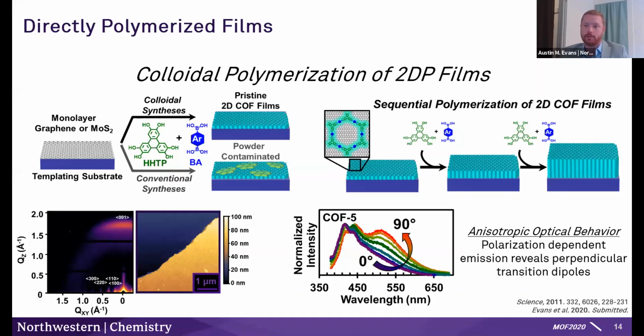grazing incidence diffraction. Interestingly, if you attempt to do this on films that were grown via our old method, where we had a small amount of powder contamination, that small amount of powder contamination really complicates the anisotropic optical behavior, because the unoriented crystallites on the top seem to contribute more than the whole film itself. Okay, so this seems like a promising method to make oriented, really nicely defined films on a variety of substrates.